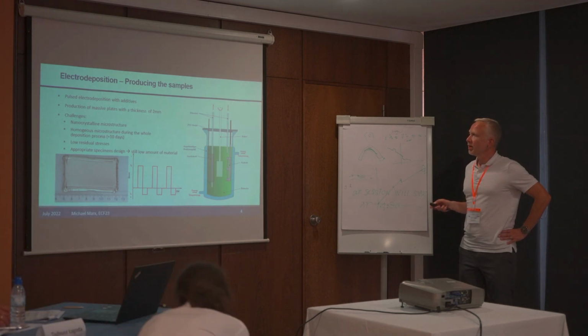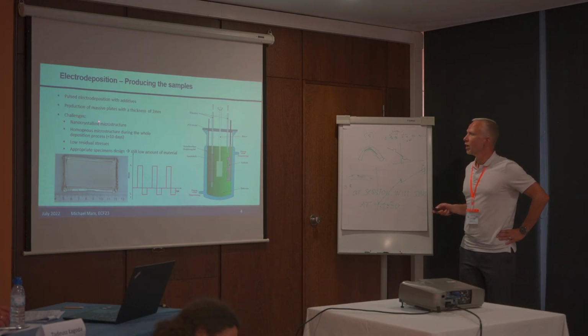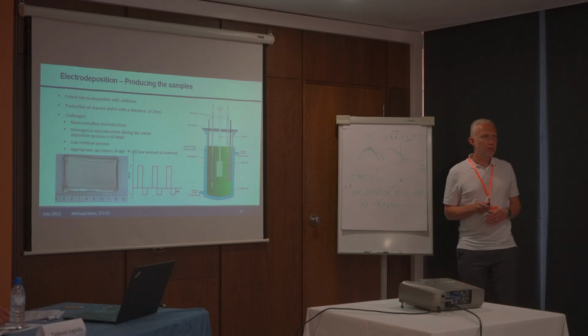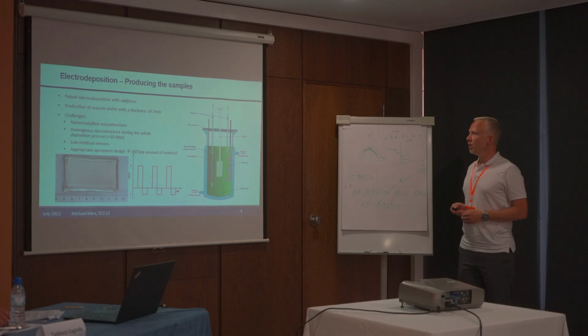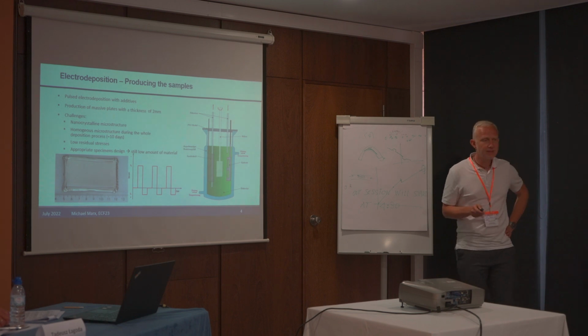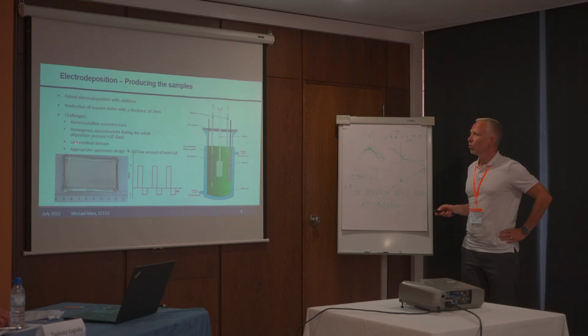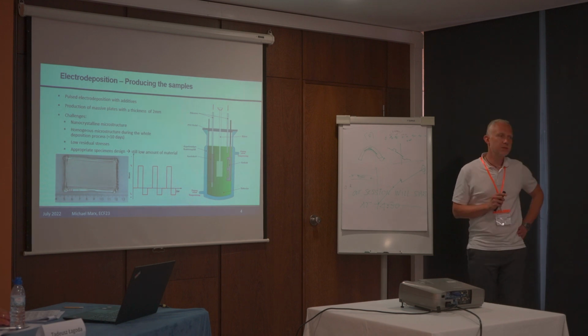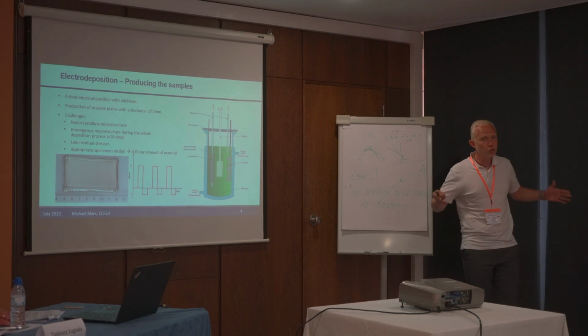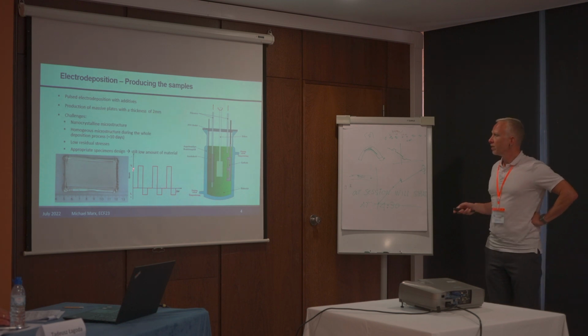The thickness of the plate can be up to 2 millimeters, and the challenges are to get a nanocrystalline microstructure, to get a homogeneous microstructure for this whole 2 millimeters, and during the whole deposition process, which lasts 10 days, we want to have low residual stresses, and we need an appropriate specimen design because the amount of material is still low, so we do not produce huge plates. And we make it here by a pulsed electrodeposition.